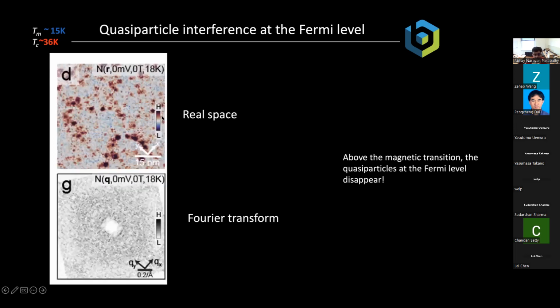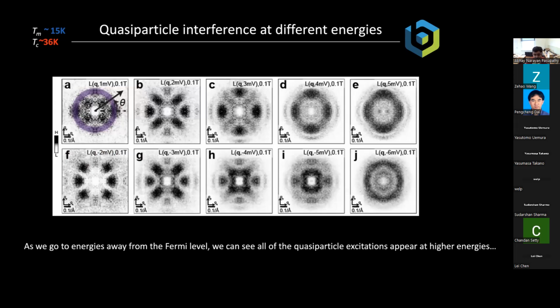Now, we can go above the magnetic transition, where, remember, I told you all of these phenomena go away. And indeed, if I go above the magnetic transition and I repeat the same measurement, all of these quasiparticles at low energy disappear in our interference patterns. And this is also consistent with our idea that the magnetism is really responsible for driving this unique superconducting order.